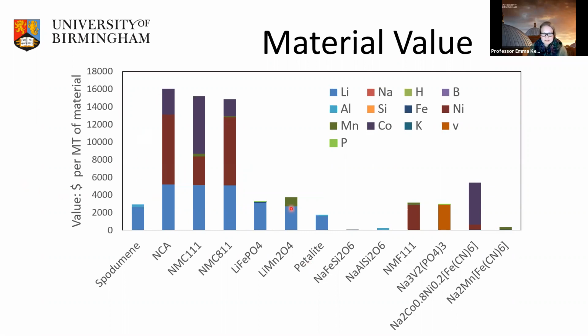And here I've just plotted out some standard cathode materials for lithium-ion batteries. So we've got NCA, which is nickel, cobalt, alumina. NMC, nickel, manganese, cobalt, 111 and 811. We've got lithium-ion phosphate here, lithium manganese oxide spinel. And I've also compared the value of the metal components of those materials. So the blue here is lithium. We've got the purple at the top is cobalt, and the red is nickel, and a little bit of green that you see in here is manganese.